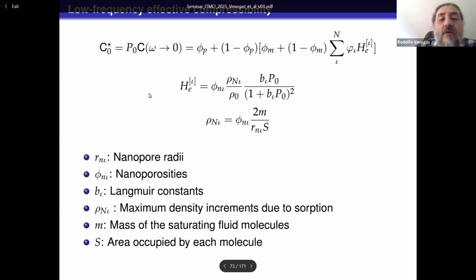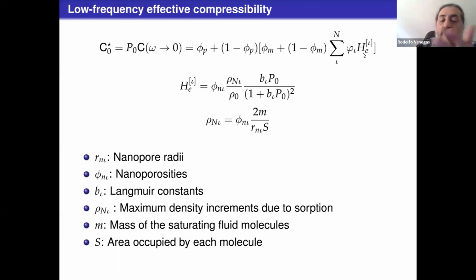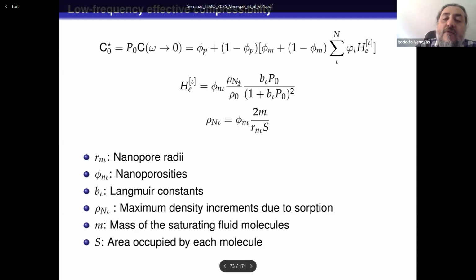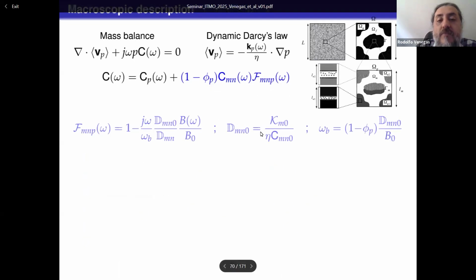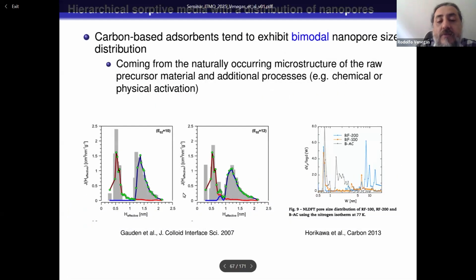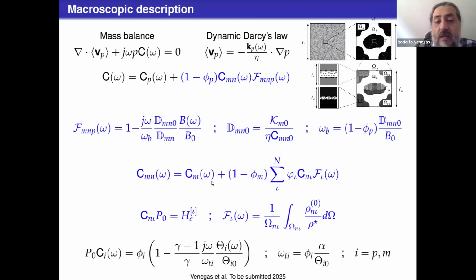So if we look at what happens at low frequencies, this depends again on the linearized sorptive effective equilibrium constant related to each nanoporous patch, that can be related to the Langmuir model in this way. That gives us a way of estimating some of the parameters with non-acoustic measurements, like for example, using the value directly of the nanopore size distribution that is measured using adsorption isotherms and then some post-processing with specific models to get this type of data. This is what we're working on now.